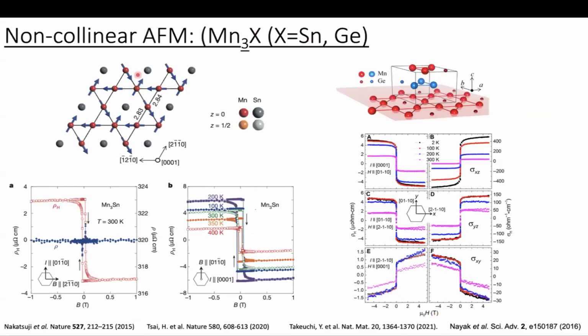Among various non-collinear antiferromagnets, in particular intermetallic systems, the first report was on manganese-3 tin single crystal by a Japanese group, Nakatsuji et al. They observed for the first time a large anomalous Hall effect in manganese-3 tin crystal, and that large anomalous Hall effect was not related to the magnetization, and the magnetization was negligibly small. And at a similar time, Nayak et al. also observed a large anomalous Hall effect in a sister compound, manganese-3 germanium.